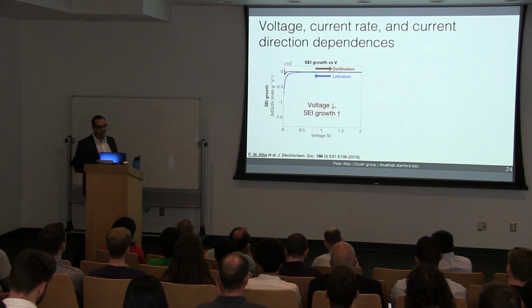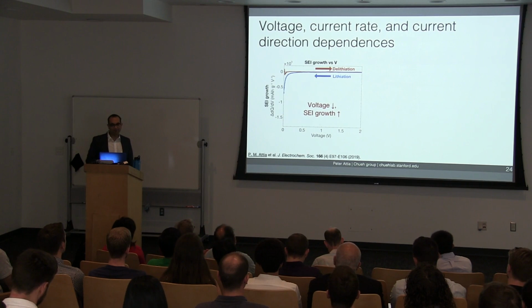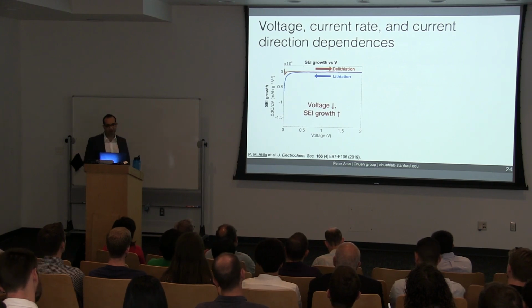I don't have time to discuss the details, but I developed an electroanalytical technique to isolate the electrochemical signal of SEI from that of carbon black. I'm going to use this technique to measure electrochemical dependencies of SEI in voltage, current rate, and current direction. This plot shows how SEI grows as a function of voltage. We find that SEI growth dramatically accelerates if we go to low potential during lithiation. It has roughly an exponential dependence. But during delithiation, however, the growth is near zero.